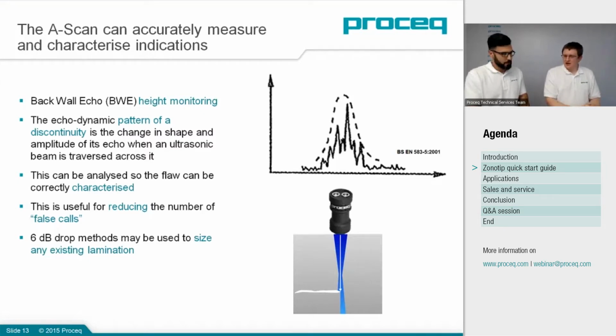Another application for using the A-scan is to monitor the signal from any indication you get. We did an application about a month ago where we were looking at some plate material which had a number of indications. When you use the A-scan function, you could see that a number of these indications were from porosity. In the top right drawing, you can see a typical echodynamic envelope you get from porosity. We weren't interested in that; we were looking for delaminations.